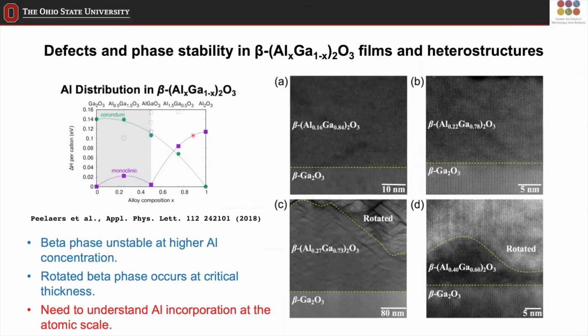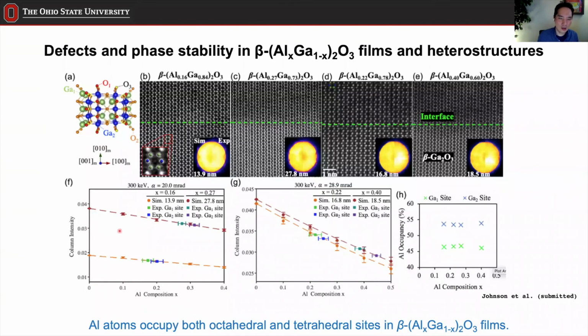But that's the case of bulk, and this is thin film, so there's a difference, right? So maybe what's happening is, in this thin film growth where things are non-equilibrium, the aluminum atoms may occupy the other sites too, which are tetrahedral sites. So we wanted to understand that aluminum incorporation, whether they actually go into tetrahedral sites or not, okay? So that's what we wanted to do, and we did that. Again, there are a lot of details here which I can't explain all in the limited amount of time. But what we basically did was the same quantitative STEM intensity analysis for all these samples having different aluminum concentrations: 16, 22, 27, and 40%.